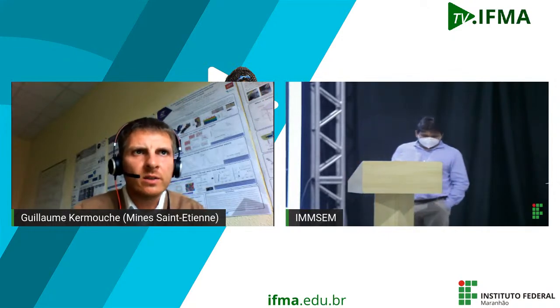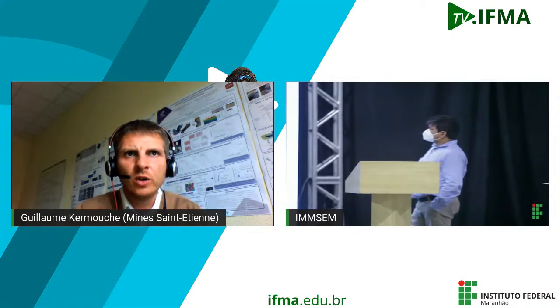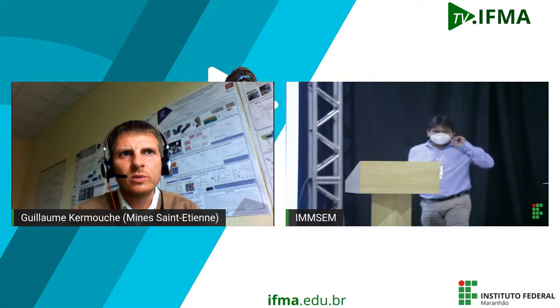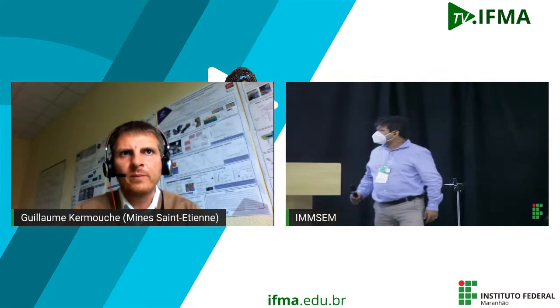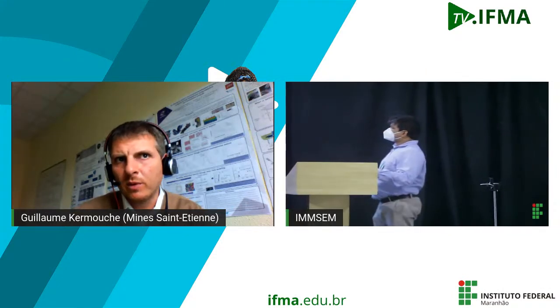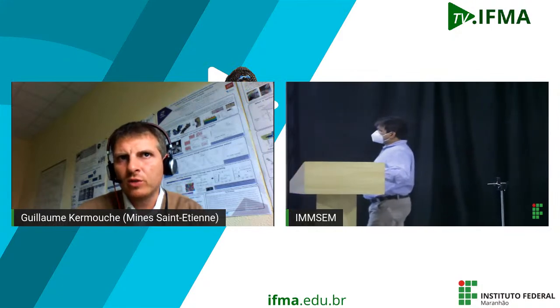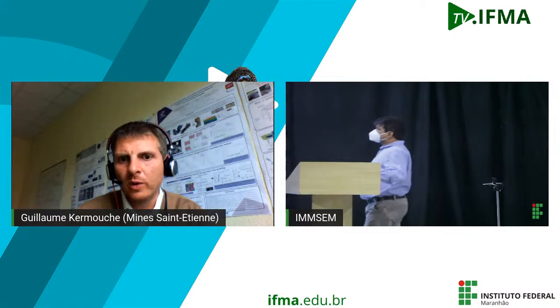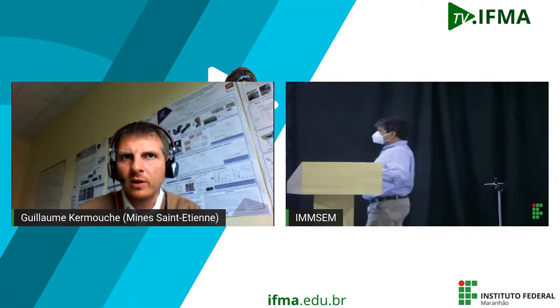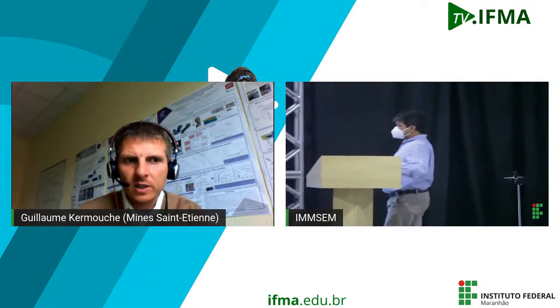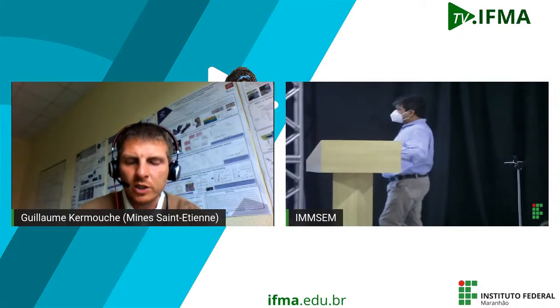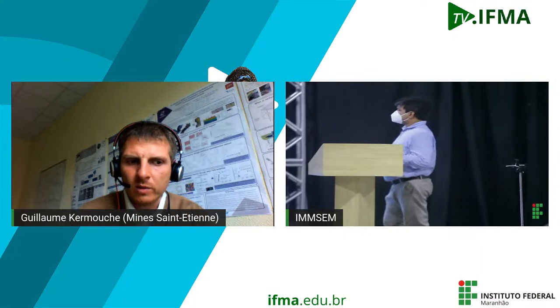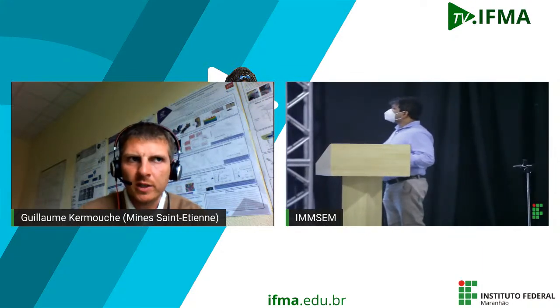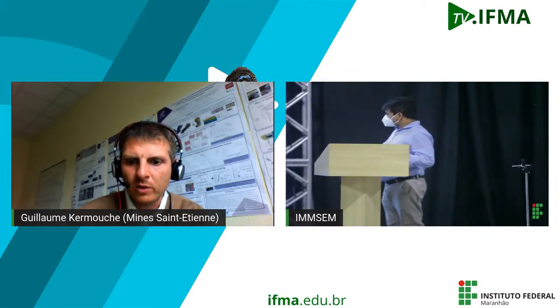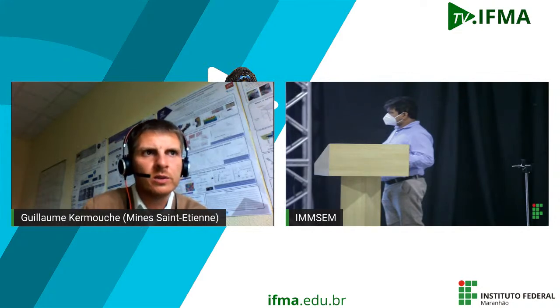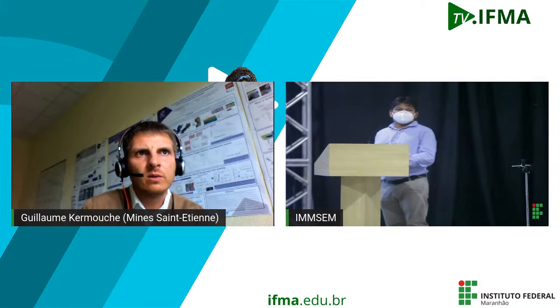So I wouldn't say that the hardness is lower for non-recrystallized materials. If you look at this result, so I go back to this one. Here it's the hardness of the recrystallized sample, and here it's the hardness of the initial material. So yes, you have a decrease of the hardness with recrystallization, a lowering of the dislocation density. What is very surprising with tungsten is that usually for most metals, when there is recrystallization, that means that the material is softer, but it also means that the material can resist ductile damage. And this is not the case of tungsten. So in the case of tungsten, if I try to go back to this slide, that's something that can be interesting for you.